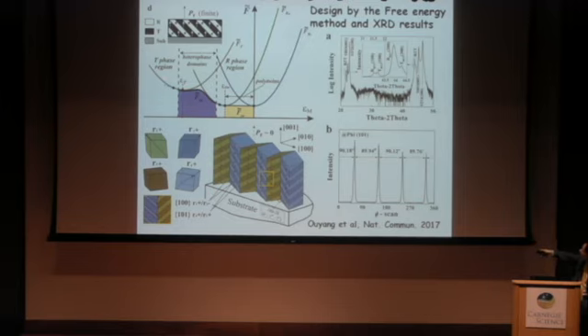But when you put it on a substrate, there's a certain misfit range where the mixed phase becomes more stable, right? I don't need to say more about it. People already know it in the bismuth ferrite case. But you can see when the misfit strain is higher, it's close to the self-strain of the tetragonal phase. So the dominant polydomain structure will be a tetragonal-rhombohedral mixed phase, just like in the case of bismuth ferrite.